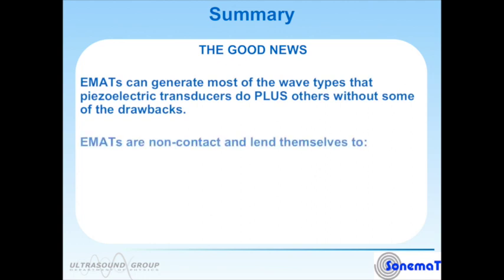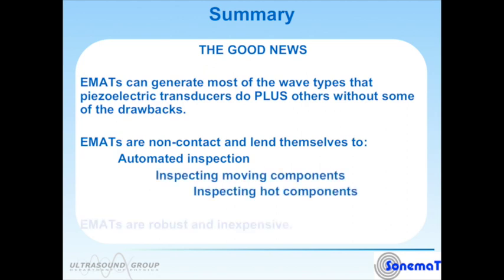The good news when it comes to EMATs, well, EMATs can generate most of the wave types that piezoelectric transducers can, plus a lot of other different kinds of interesting wave modes without some of the drawbacks. EMATs are non-contact devices, and as such they do lend themselves to automated inspection, inspecting hot or moving components. They can be made in such a way that they're robust and inexpensive. So EMATs are not always the right solution for every situation, but because they offer some very unique advantages, in many cases they should be considered as a way of inspecting a sample or a material.